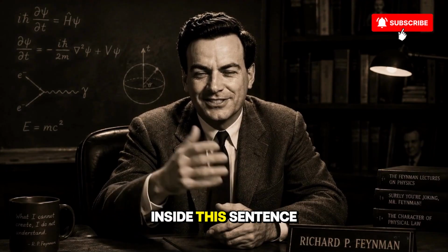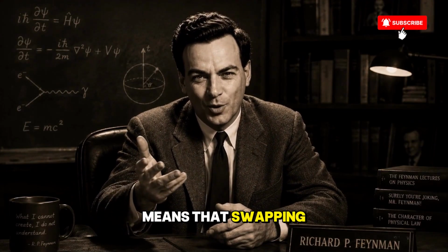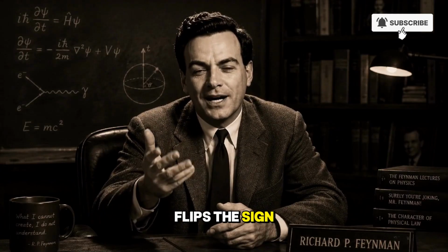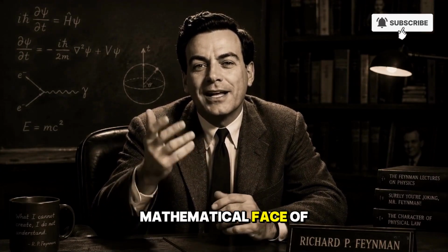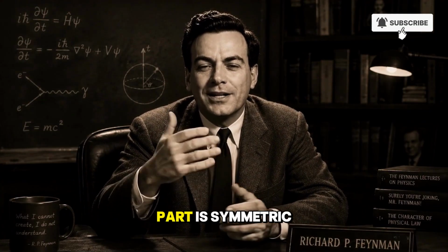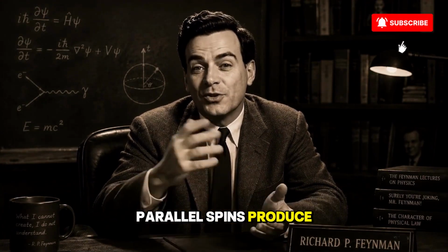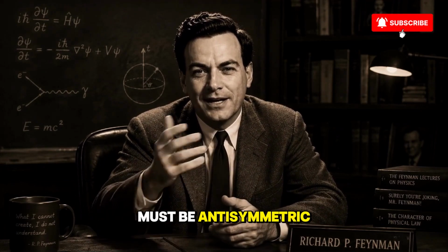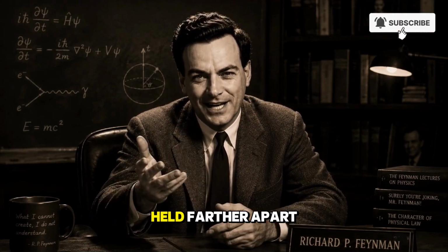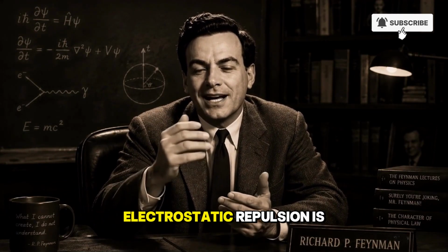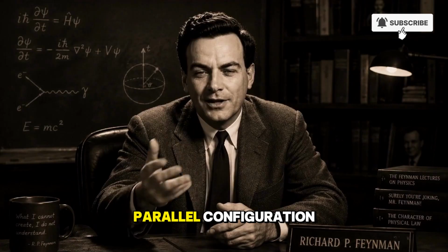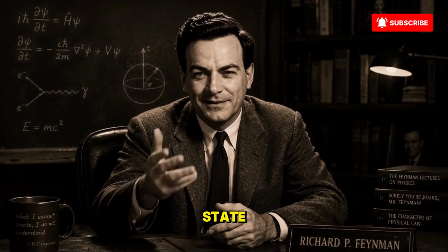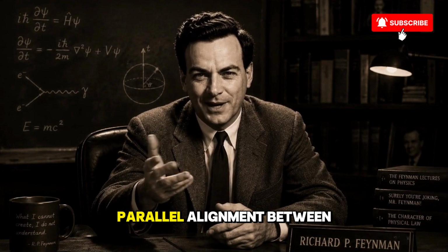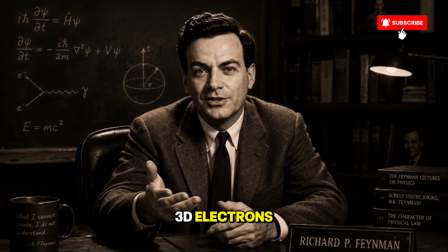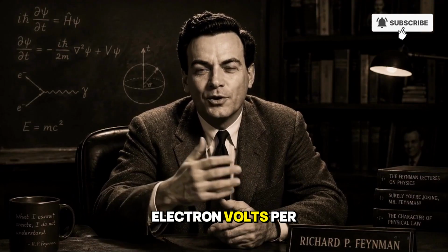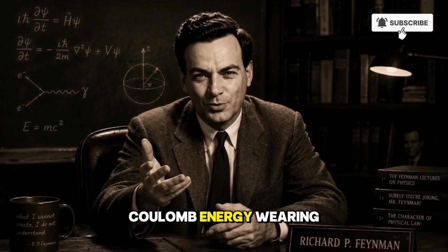Define that term inside this sentence. Antisymmetric means that swapping the labels of two electrons flips the sign of the wave function, which is the mathematical face of the Pauli principle. When the spin part is symmetric, which is what parallel spins produce, the spatial part must be antisymmetric, which means the two electrons are statistically held farther apart, which means their electrostatic repulsion is lower, which means the parallel configuration can actually be the lower energy state. In iron, the energy gap that favors parallel alignment between neighboring 3d electrons is on the order of 0.1 electron volts per pair. That is a Coulomb energy wearing a Pauli mask.